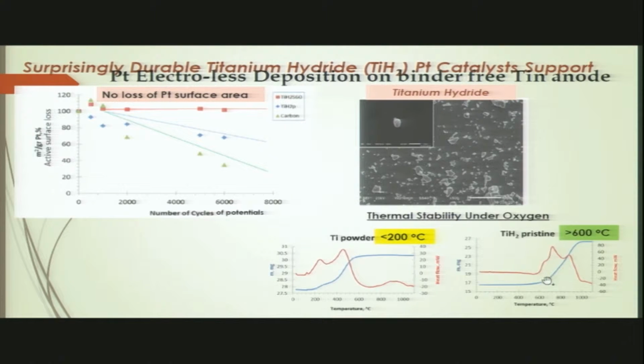environment. Here you can see, for example, this is the thermal analysis that shows that titanium hydride decomposes above 600 degrees C, while even titanium decomposes below that, or oxidizes. It's not decomposition, it's an oxidation. So we use this material and we place platinum particles on it, and here you can see the red line showing 100% of retention of the original surface area of the platinum, while carbon and even untreated material of the same structure were not good enough.